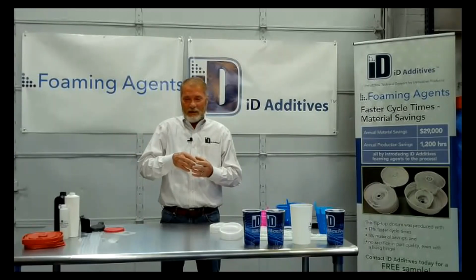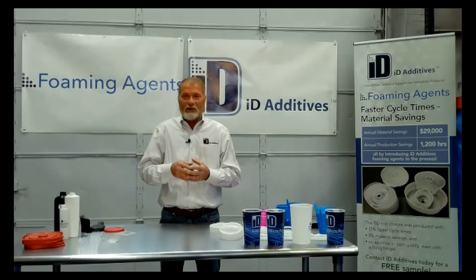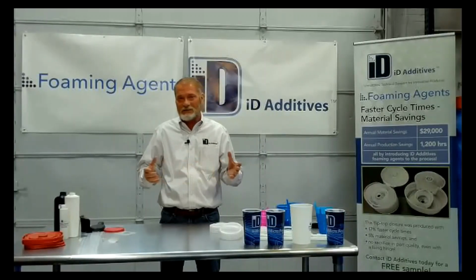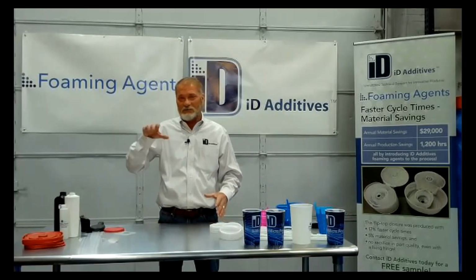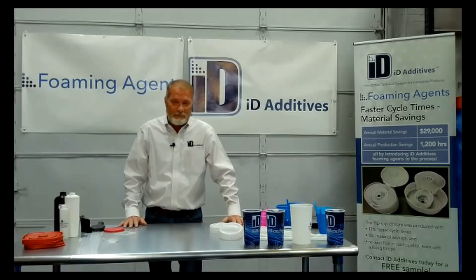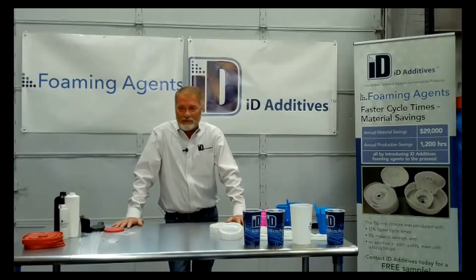So sometimes a little longer cycle time fixes that. Maybe even a little cooler temperatures. It depends on what kind of surface you're looking for too, as far as mold temperatures. But you can take out anywhere, it just depends how fast you get it. You could take anywhere between 6 and 12% weight out.